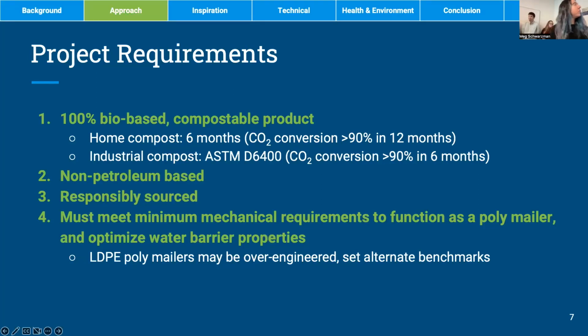So we consulted with Sway to assess their priorities and determine the framework and constraints of our approach. So central to Sway's mission is that their product must be 100% bio-based and compostable by both home and industrial standards. So this is measured by the percent carbon dioxide conversion over time listed here. And field tests of Sway's current material suggest that it completely disintegrates within 48 days. So this places their current product well below these listed cutoffs, which is a great point to highlight and consider because each of our proposed solutions vary in the extent to which they alter biodegradation rates, but their starting product is well below these goals, and the hope is to keep it that way.